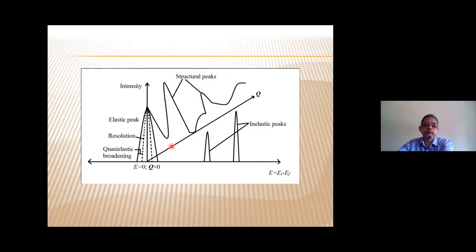So this is the elastic scattering part, Q, where you can see the Bragg peaks, and structural part you can determine. Whereas if you do the energy analysis, you can see the inelastic peaks coming up because of the periodic motions of the atoms, and because of the exchange of energies between the neutron and the nuclei, you can see that these are coherent inelastic peaks coming up here. And so this is how the power of neutron scattering lies.